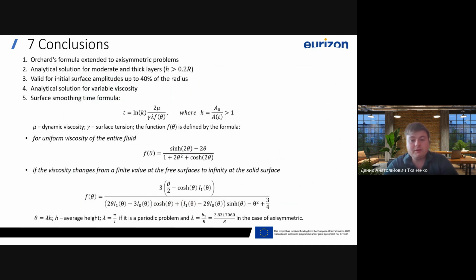To conclude, we have extended Orchard's formula to address axisymmetric problems, allowing us to develop an analytical solution that aligns well with numerical results for moderate and thick layers, where the thickness exceeds 20% of the radius. This solution remains accurate for initial surface amplitudes up to 40% of the radius. We also derived an analytical approach for variable viscosity across the liquid layer, which applies to both periodic and axisymmetric problems. This provides us with a straightforward method to calculate the time required for surface smoothing.